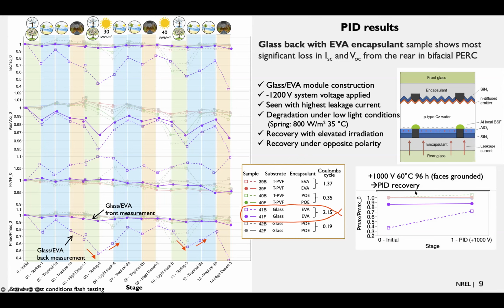So just to kind of confirm our hypothesis that it is PID, at the end of the test, we took the module out and biased it under the opposite polarity, positive 1000 volts. And this particular purple module, the module with purple points, quite significantly recovered with application of 1000 volts.